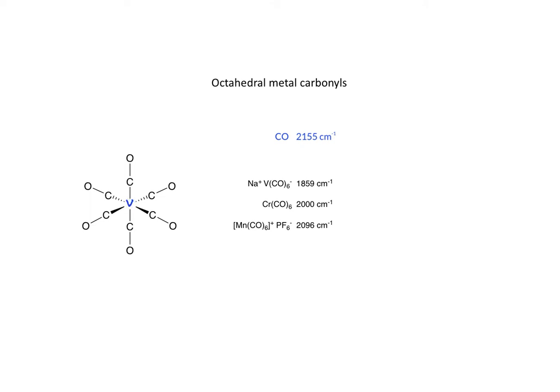If the metal is vanadium, vanadium in the -1 oxidation state has a formal negative charge, which is distributed throughout this complex. But the negative charge from an additional d electron in the group 5 metal center provides more electron donation for back bonding, decreasing the bond order of carbonyl. And this is revealed by the infrared stretch at 1859 wave numbers, greater than the bond order of a ketone, but probably closer to bond order of 2 than to 3.